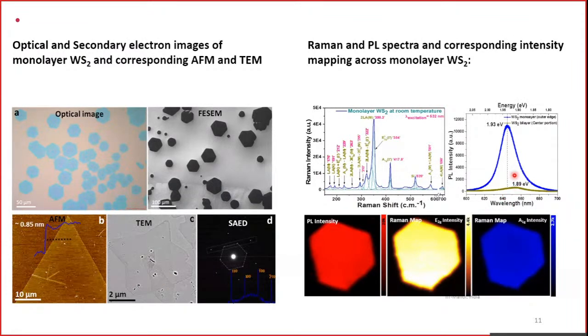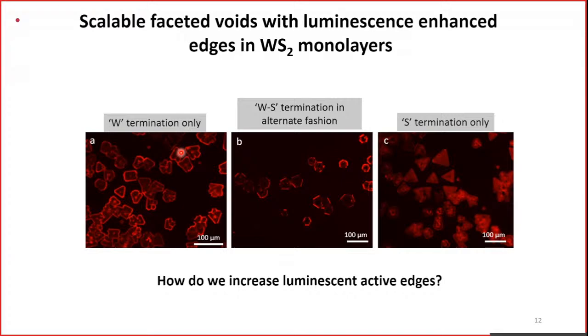In addition to that, you see the PL is getting quenched because there is a transition from the direct band gap to indirect band gap. Starting from the third layer, you would not see any emission at all, right? That is because of the direct to indirect band gap transition. We also do the PL mapping just to make sure there is a uniform monolayer present in our case.